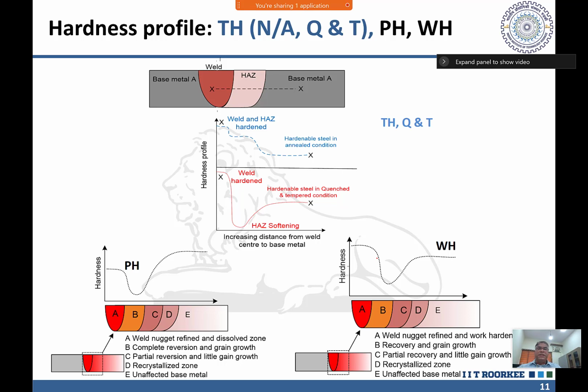Okay, so if you take steel in Q&T condition, it shows a lot of softening in the heat affected zone. Weld may be hard, it's fine. On the other hand, for steel in annealed condition, you see the weld is harder, then it is a little softer, then it is softer, like this. So there can be a lot of variation. You change the metal, if you bring two different metals, precipitation hardenable metals will show a lot of softening. Weld is also weaker than the base metal. On the other hand, work hardened metals may be stronger than the base metal, and the weld is softer.